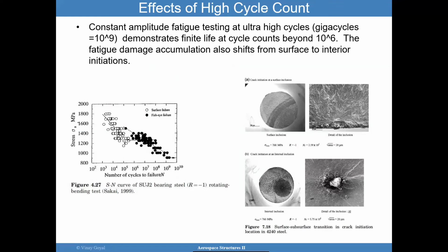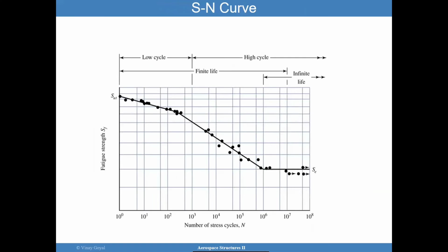I want to point out that when you go to ultra cycle fatigue, giga number of cycles, it's possible that even though you thought you have infinite life, you could start having some amount of fatigue failures. People have seen that crack initiation and propagation can occur after a large number of cycles. So you cannot completely discount the fact that that could happen in gigacycles. And again, this is the SN curve to remind you what that looks like.